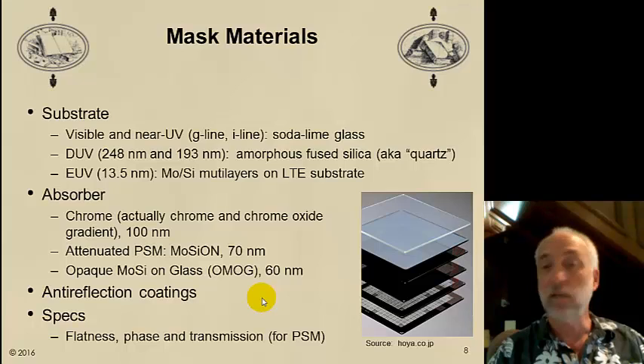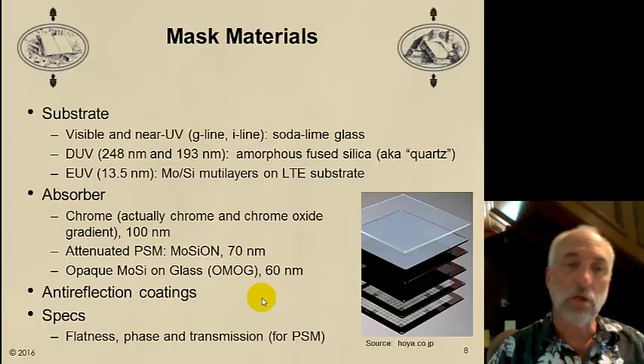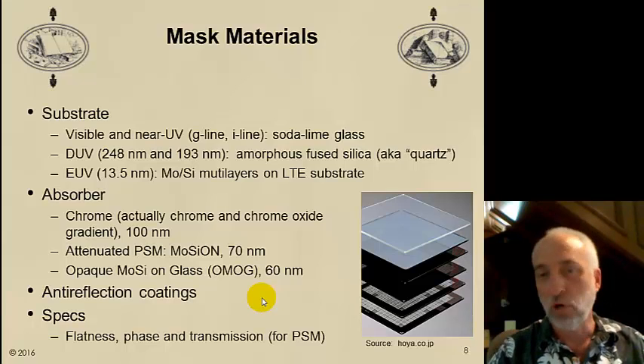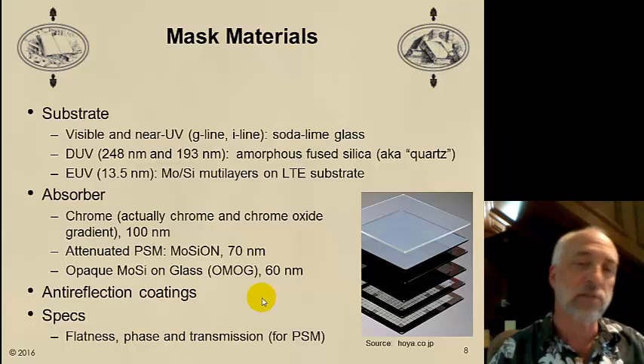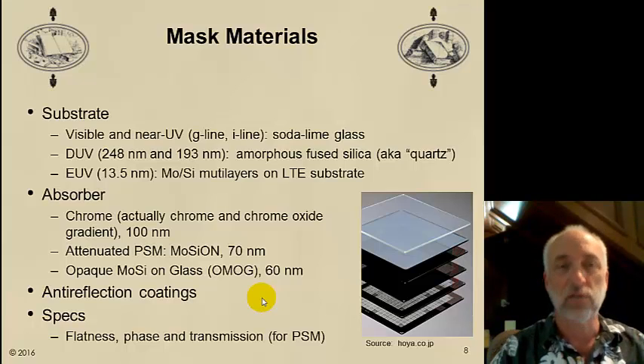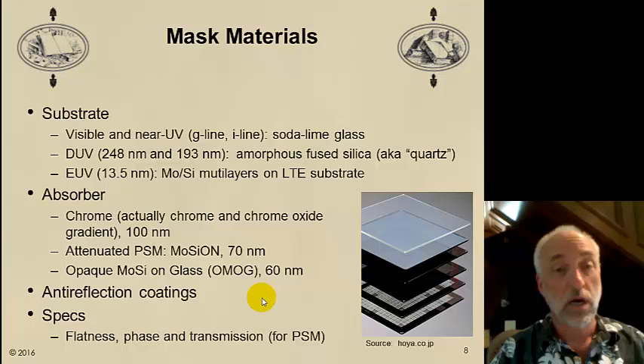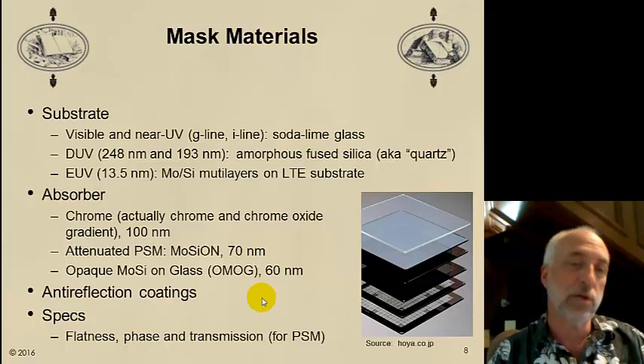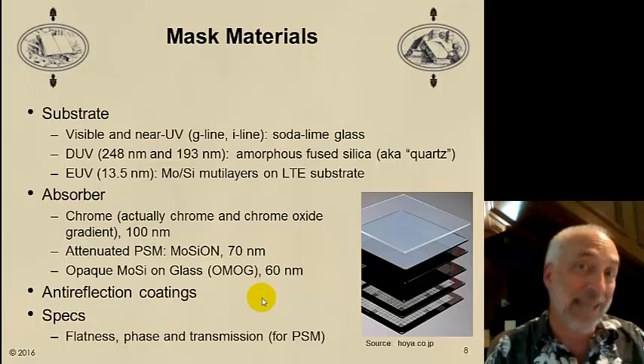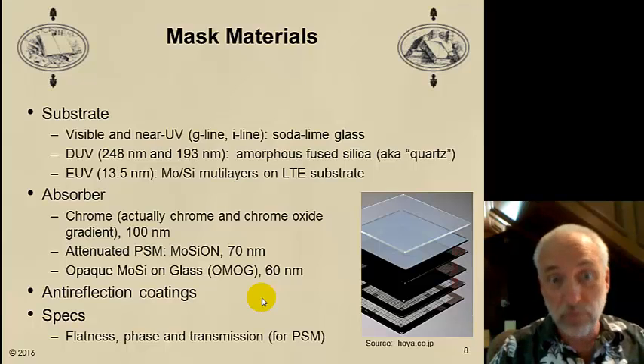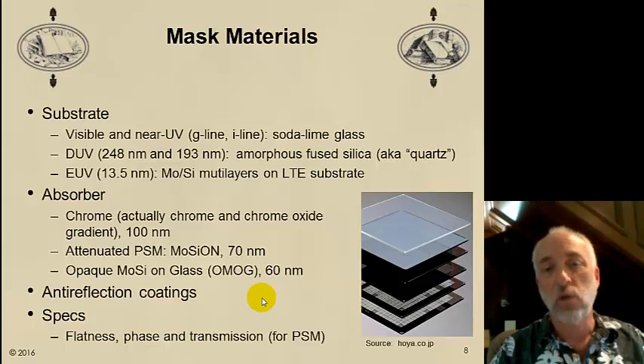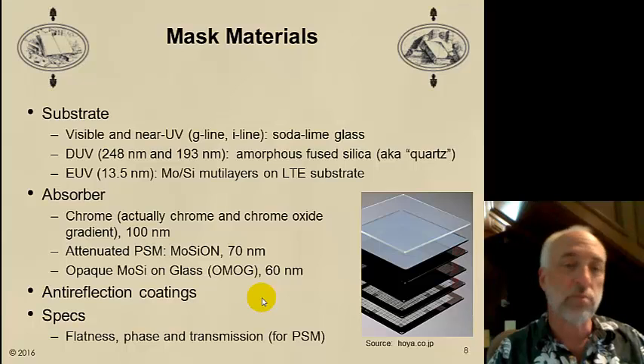Then we add an absorber. For a long, long time, we used almost exclusively chrome as our absorber. Actually, it was chrome with a gradient of chrome oxide. Chrome oxide acts as an anti-reflective coating, and is on the order of 100 nanometers thick. But chrome is kind of hard to etch, especially with a dry etching process. And so we've switched to some other materials that actually work better than chrome.